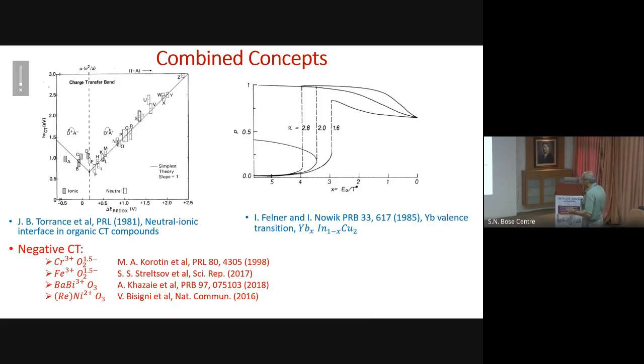All right, so I want to now draw attention, if you can read here, to one thing that is not, or very rarely, recognized in the field of oxides: the second electron affinity of oxygen, from oxygen 1 minus to oxygen 2 minus, is negative. You get the first electron easily. It does not accept the second electron. The energy you have to put in is 8 eV. So there are compounds which are called negative CT, I'm going to come back to that, in which oxygen is known to be fractionally charged. Two oxygens together have charge 1.5. And that 1.5 is a magic number that I'm going to come to.